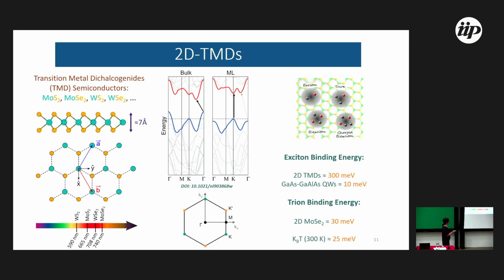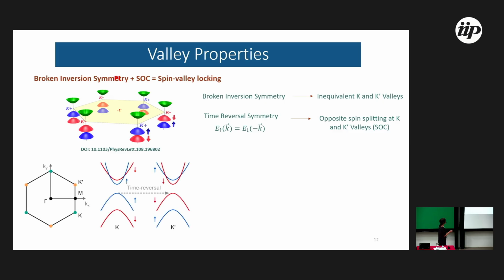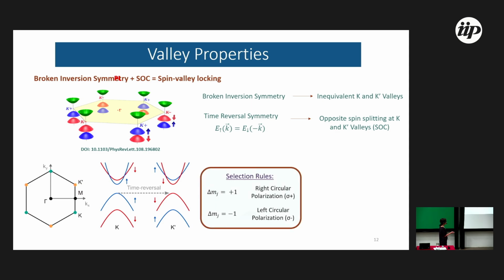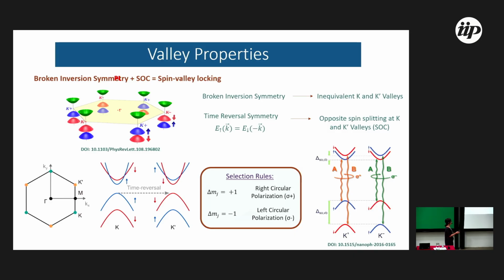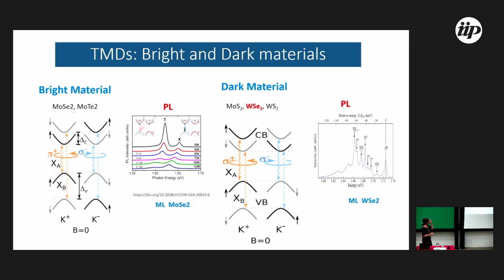And furthermore, it has very nice valley properties, because there is this broken inversion symmetry and strong spin-orbit coupling, so you have a spin-valley locking, which means that the optical transition involves circularly polarized light. The direct gaps are at the corners of the hexagon of the first Brillouin zone, and they are degenerate, but they are not equivalent in terms of spin. So you can select one valley if you use circularly polarized light, or another valley. It's the same gap, but they are not equivalent.